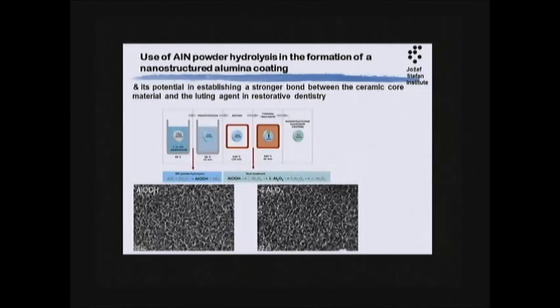I heard that much that sandblasting is not good. Sandblasting is dangerous. So then I said, okay, let's have a look. Perhaps we can get an alternative solution that won't damage the surface. So, being inventive, I used something which everybody can buy. It's aluminum nitride powder. Aluminum nitride is a powder that reacts with water, forming aluminum hydroxide and ammonia that you smell. But it's not dangerous if the concentrations are not high. And this aluminum hydroxide will form a network of lamellas perpendicular to the surface of the substrate.